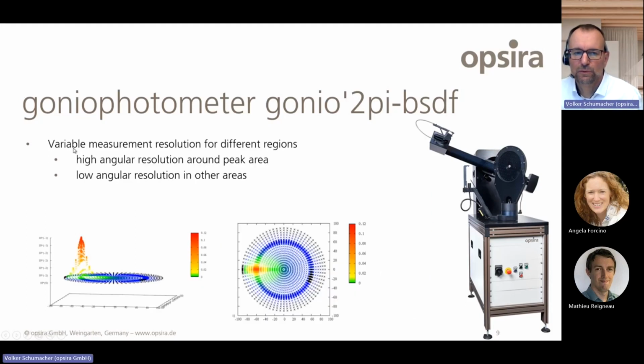Also, we can choose variable measurement resolution for different regions. Here we see a result of a measurement, and where we have the specular peak here in that area, we choose a high angular resolution, and where we have the scattered area, there we choose a low angular resolution, and so we do not have to have so many measurement points. And this can be freely chosen for every angle of incidence.